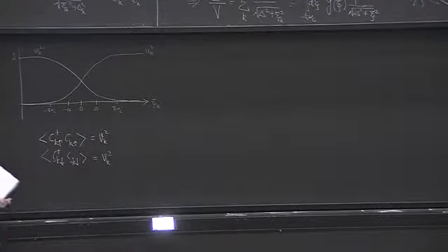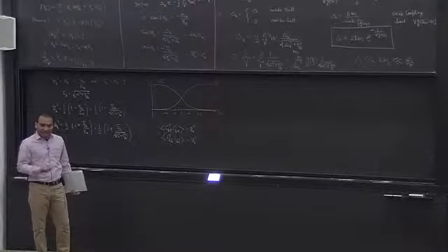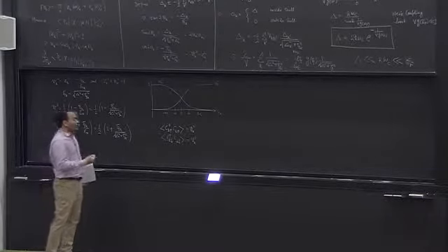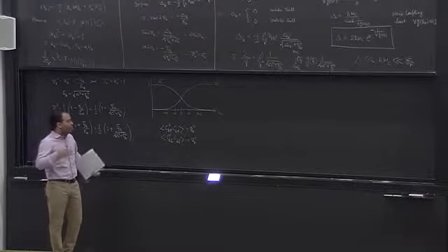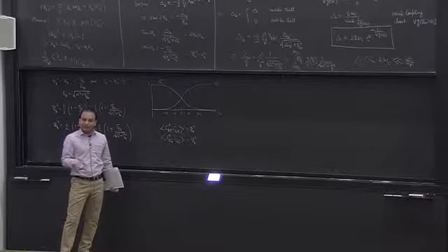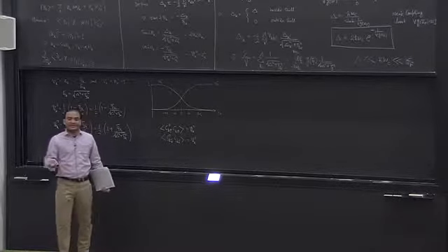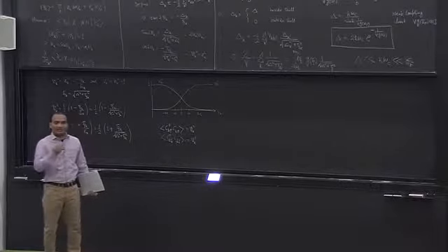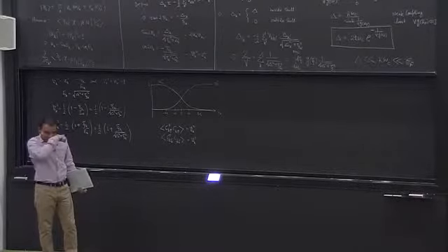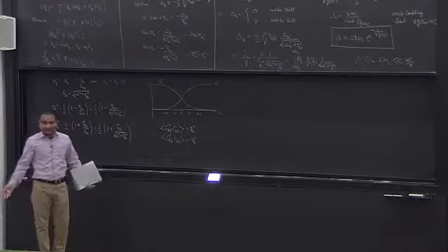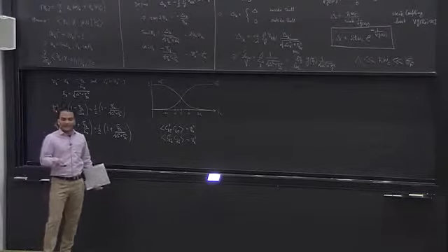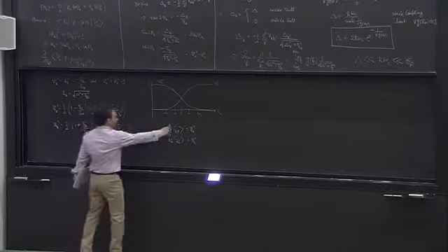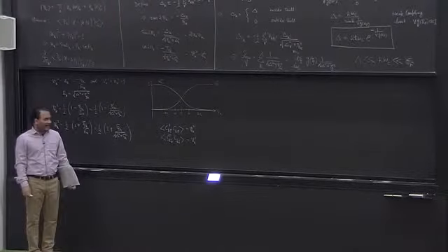So physically, we can think of Vk square as a function of k that gives us the occupation probability of single electrons also. We know mod Vk square is the occupation probability of a Cooper pair, which is one electron k up and another minus k down. If in our ground state we only have electron pairs, then this probability is also related to the occupation probability of single electrons. We did this calculation in detail on Friday.